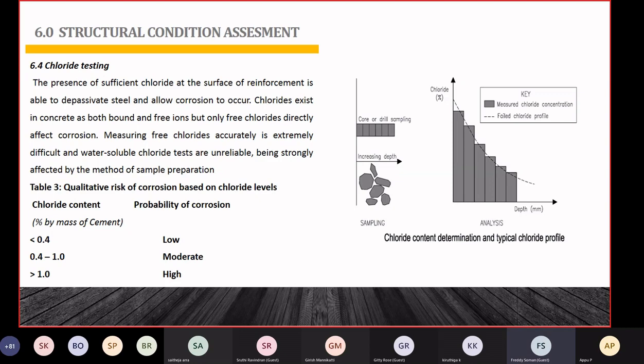Another one is the chloride ingress profile. Particularly when we want to repair, we may want to scabble some of the concrete. We want to break out and remove some of the surface and cover area. Up to what depth we want to remove, in that case the chloride ingress profile test is very important. Up to what depth it is contaminated, that part we have to remove, and we repair it with new repair mortar or new concrete. That way, chloride contamination is very important. If we do not correctly find out the chloride and we do the repair, it will not sustain, it will not last long. The corrosion activity will continue again, and it will again damage the concrete.